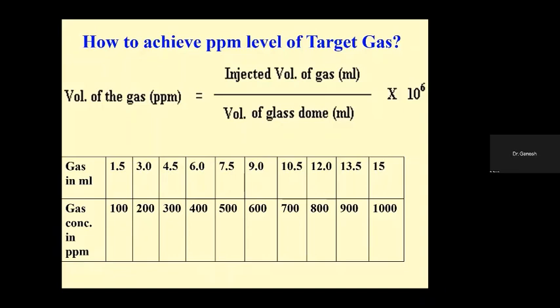The volume of the gas can be controlled manually, or otherwise it can be controlled by a flow meter. How is it achieved manually? That chart is given here. We have a glass dome of volume 15 liter. So if the gas exposed on the film is 1.5 ml, then it is 100 ppm gas concentration. If it is 3.0, then it is 200 ppm. By calculating, the gas in ppm is equal to the injected volume of gas upon the volume of the glass dome, which is 15 liter, multiplied by 10 raised to 6, so that we can convert this volume of the gas into ppm.